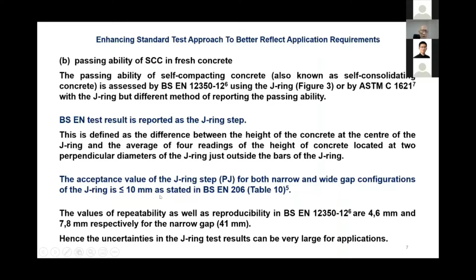But if you look at the actual height of those concrete, it's very close to that. So the values in terms of repeatability and reproducibility are given in an example, about 5 to 6 in repeatability, and reproducibility 7 to 8. That means if you do the test twice, it can differ by 5 to 6 mm, and you are controlling it to less than 10. So that means there's a lot of uncertainties in the test result. So it is not really the best test method.